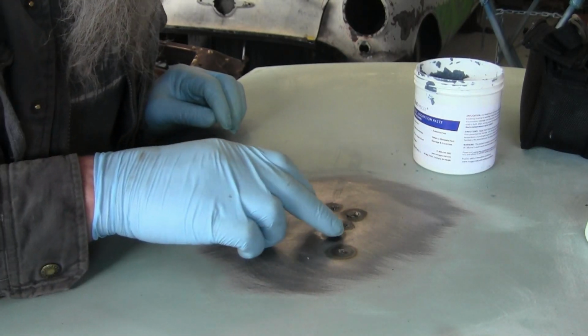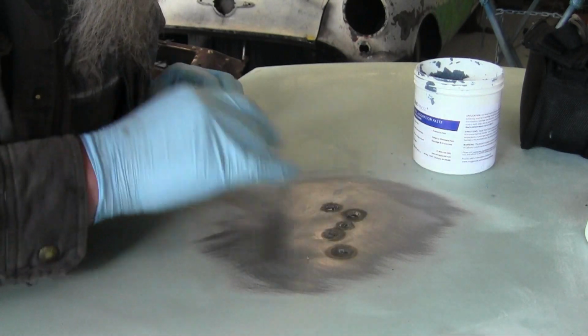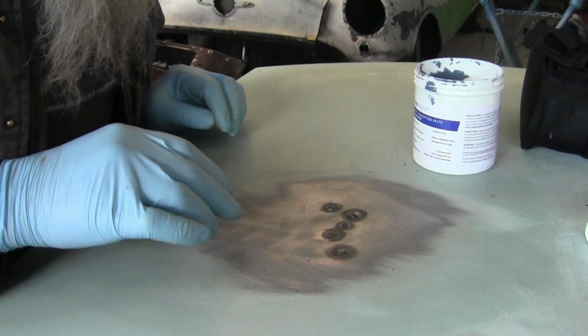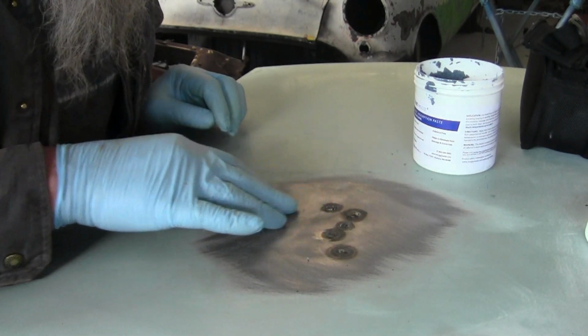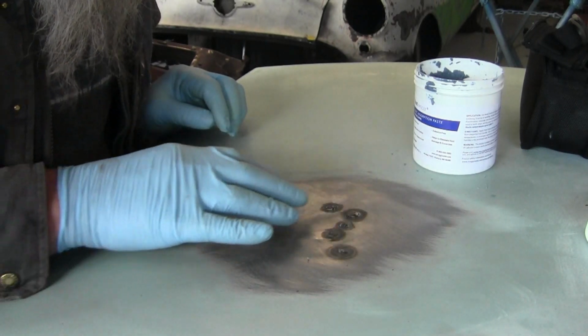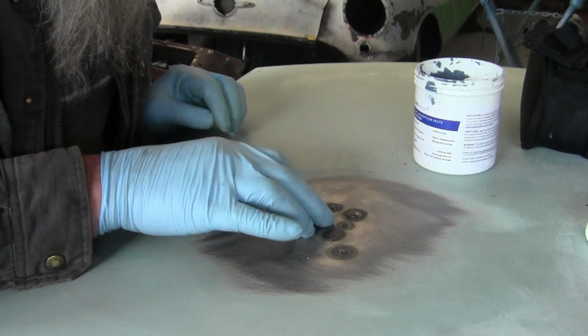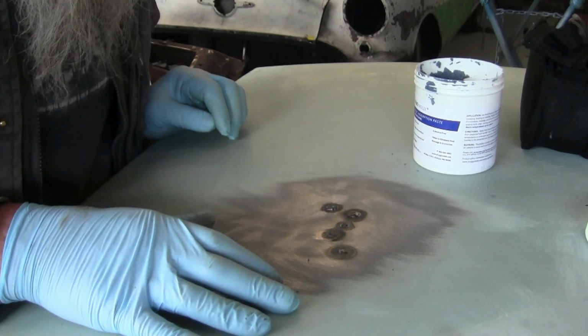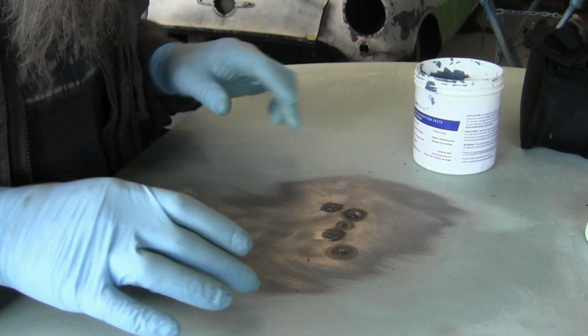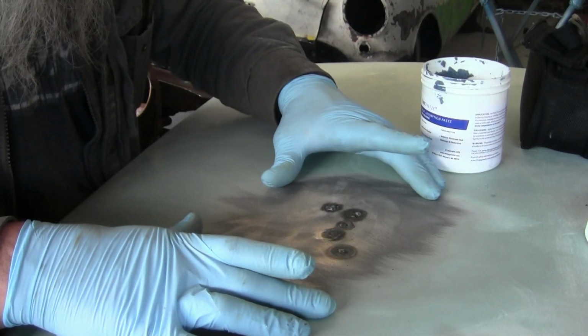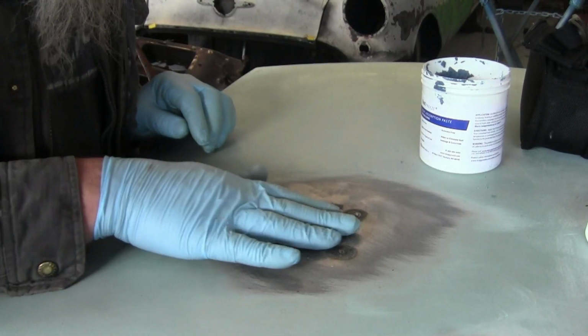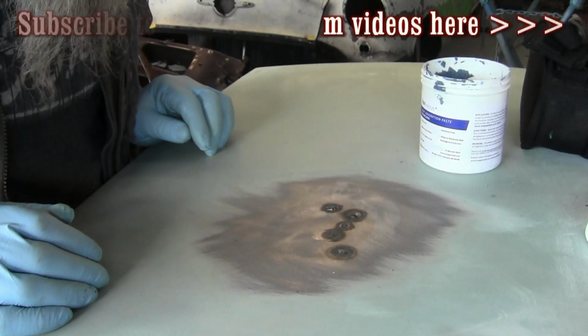Because there is a little heat affected zone around each one of them, we'll grind these down and hammer them out with a dolly, and that'll stretch them back out slightly. But the area around it has not warped much because the heat affected zone was concentrated instead of spreading out into the panel like most times when you weld. Your heat would be clear out into here by this time. And right now I can put my hand right on it after we've just welded it a minute ago or less.